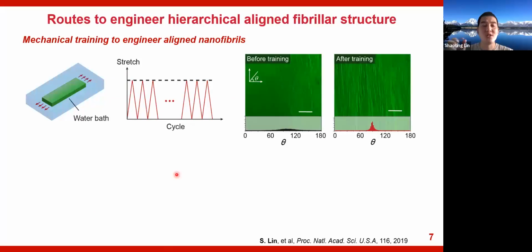The second question is how to engineer hierarchical aligned fibrous structures in synthetic hydrogels. The first technique is mechanical training. What I found is that after cyclic mechanical training in a water bath, the original random fibers inside the hydrogel can be trained to align towards the training direction. The water acts like a plasticizer to enable the reforming process of the hydrogen bonds. And we find that such aligned fibers or fibrils can effectively pin the fatigue crack propagation.